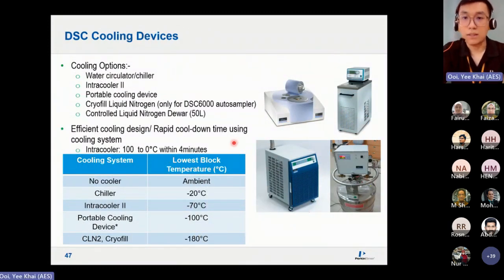As for DSC, a very important thing is the cooling devices. So how low can you start? Most of the time you are reading Tg, the glass transition temperature, and Tg is usually at very, very low temperature. So you need the corresponding cooling accessories to allow you to start at the temperature that you want. For the heat flux, we have options. This is what we call a portable cooling device. You can start at -100 because this is filled with liquid nitrogen. Of course you can opt for a chiller as well, so depending on what you mix into it, you can start at -20 degrees C. But most of the time people don't really use a chiller for DSC because the starting point is not low enough for the applications you are running.